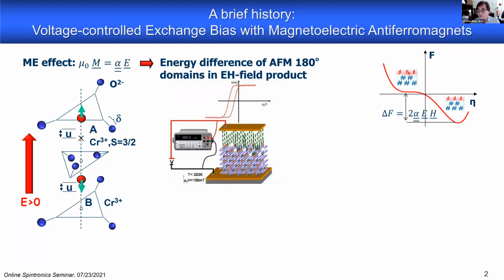And that is a finding that microscopically maybe came first from Dzyaloshinskii, and then Kirill Belashchenko put it in a symmetry-based general argument where he did show that if you have a system that is magnetoelectric or has the symmetry prerequisites that allow for linear magnetoelectricity to appear, then this system has this boundary magnetization as a consequence of that. At least that boundary magnetization is symmetry allowed. So that was a very important finding for everything that comes next.